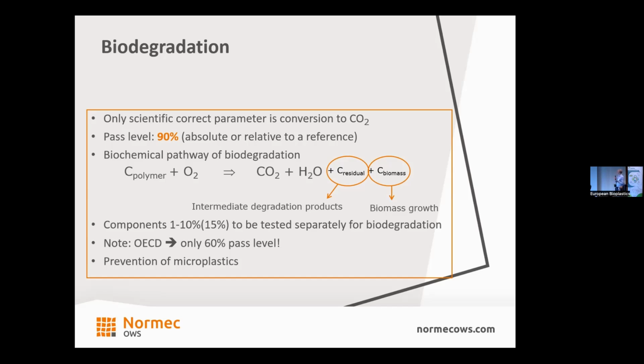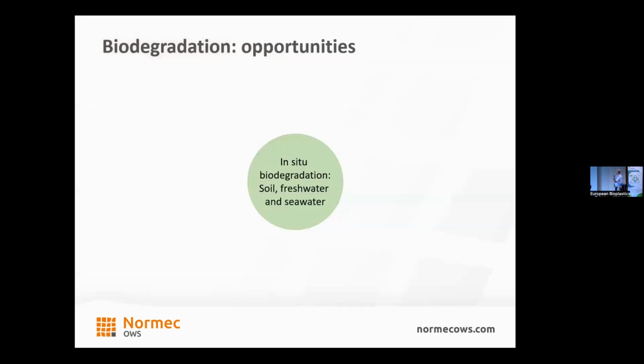In OECD, which also has guidelines on biodegradation, OECD is mainly for chemicals. There you only have to reach the 60% pass level. But for us, if you have 90% biodegradation, it's a proof of complete biodegradation, and you have no microplastics in the environment that occurred. So that's beneficial compared to other conventional plastics.